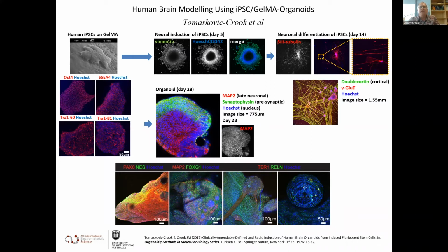Now, consistent with recent reports of optimal substrate stiffness for iPSC survival and induction of neuronal cell fate and neurite protrusion, the GelMA is mechanically tuned for a softer gel that is less than 500 pascals, also resembling the physiological stiffness of brain tissue.